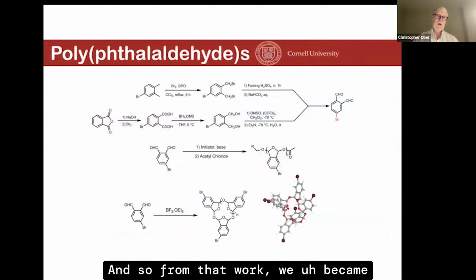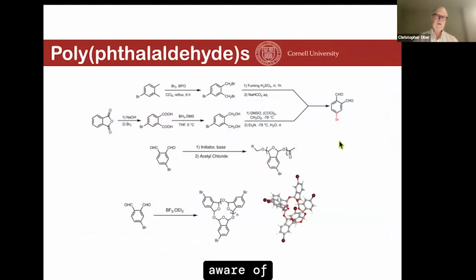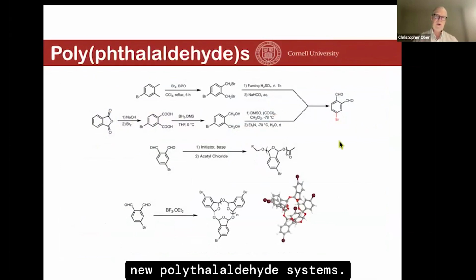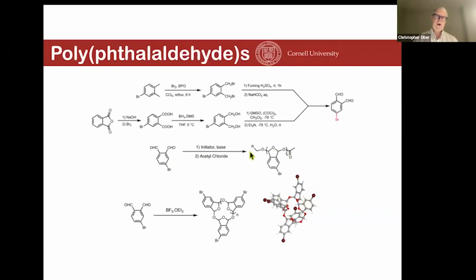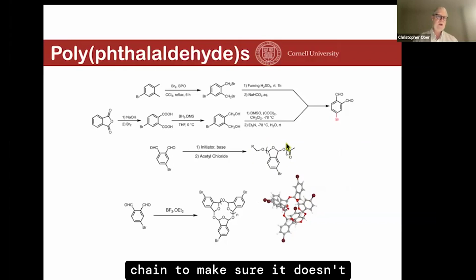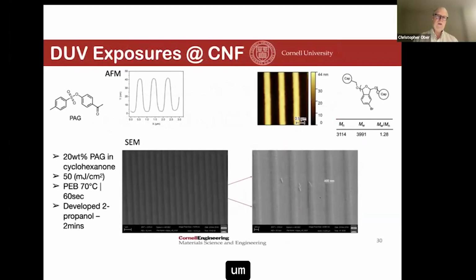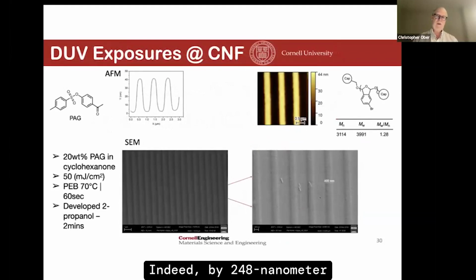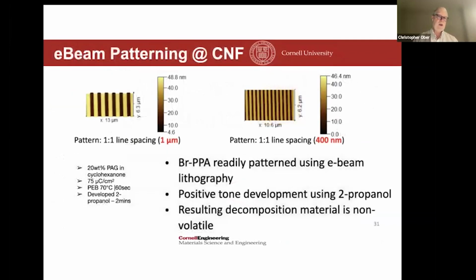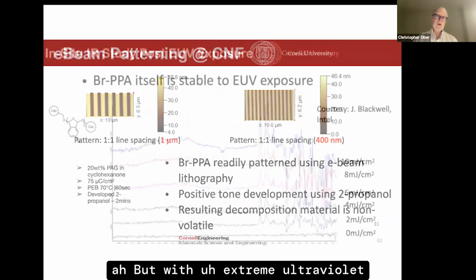And so from that work, we became aware of new poly(phthalaldehyde) systems. In this case, we put a bromine on this particular molecule, and it completely changes the character of the polymer chains. We can have linear polymers, we can have cyclic polymers. The advantage of this, it has no end groups. Here we have to cap the polymer chain to make sure it doesn't depolymerize. And indeed, with 248 nanometer lithography, a non-ionic photoacid generator forms a nice pattern. We can use it with E-beam exposures.